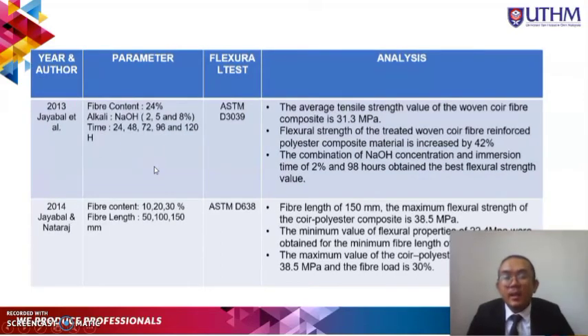Alright, Jayabalan conducted a study, and the average tensile strength value of woven coir fibre composite is 31.3 MPa. It was found that the combination of sodium hydroxide concentration and immersion time of 2% and 98 hours obtained the best flexural strength value.